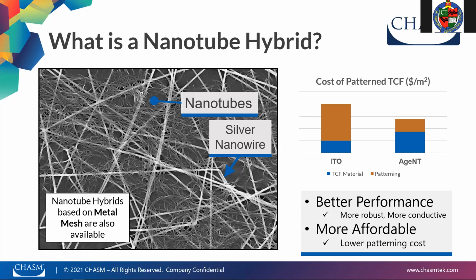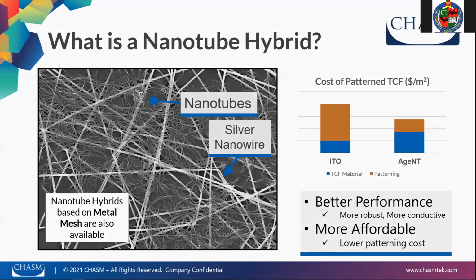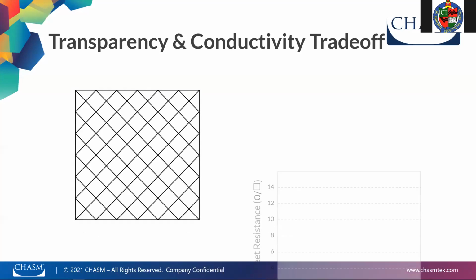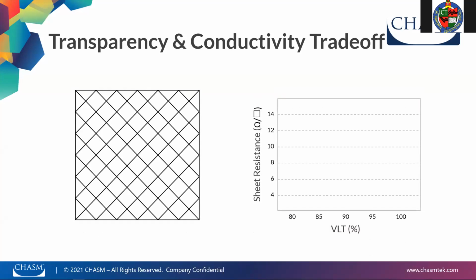Nanotube hybrids can actually achieve better optoelectronic performance with fewer conductors. So they are more conductive and more transparent than their commercial alternatives. To help explain a little bit the difference or the connection between transparency and conductivity, transparent conductive films have some rating of sheet resistance and transparency. In this case, it's measured in VLT. This rating is achieved through the interaction of the conductor density and the open areas remaining on the film to arrive at some prescribed value.